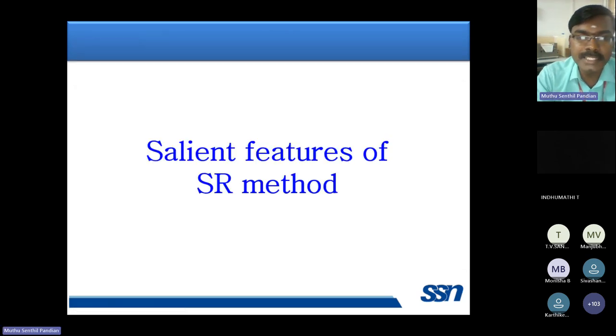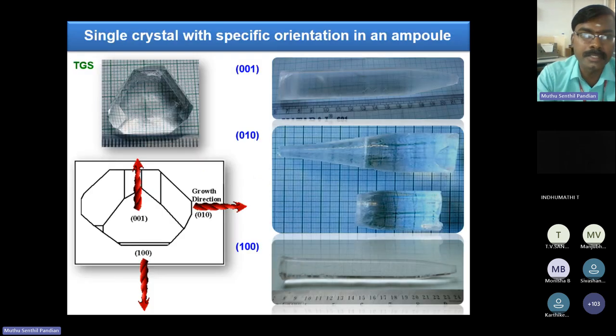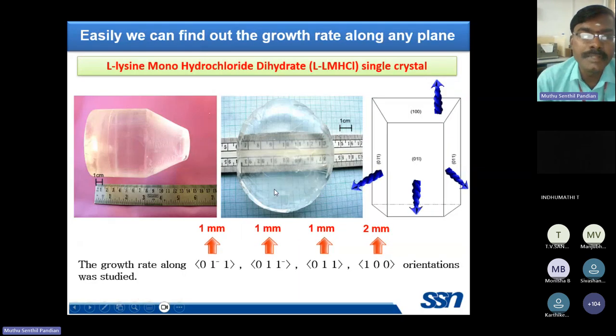So what are the advantages when we grow the crystal by this SR method? Single crystal with specific orientation in a glass ampoule. So we wish to grow the crystal along its C direction, B direction, A direction, along whatever direction, whatever plane, whatever facets you want, you can grow by this SR method. So easily we can find out the growth rate along any plane.